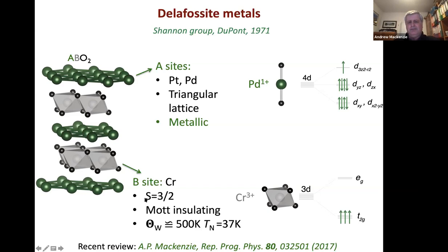Either for in-plane or interplane reasons, there's quite a high frustration parameter. The Weiss temperature is about 500 degrees and the Néel temperature a factor of 10 below that. So this Mott insulator, highly conducting metal type, in natural heterostructure, is tremendously interesting in its own right. But it would be a topic in itself. So while I'll touch on it today, I won't say much about it. And most of what we're going to talk about will be the non-magnetic cobalt-based materials.